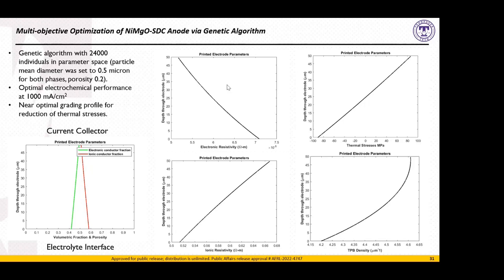We also looked at a nickel MgO with basically a magnesium oxide and a samarium doped ceria anode, and again fed this into the genetic algorithm, sorting through 24,000 individuals in the parameter space and imposing a current density of 1,000 milliamps per centimeter squared, and then optimizing to that. We find here that this individual satisfies both the criterion of minimizing the thermal stresses and also minimizing the polarization resistance as well. This study developed a very sharp Pareto front because this individual and many other brothers and sisters that had virtually the same properties were all found to result by the final generation.